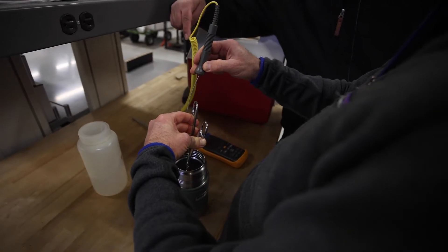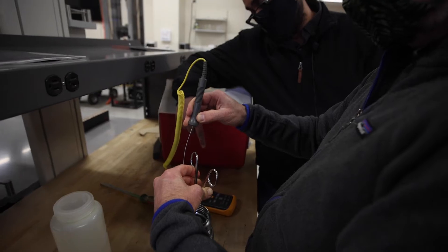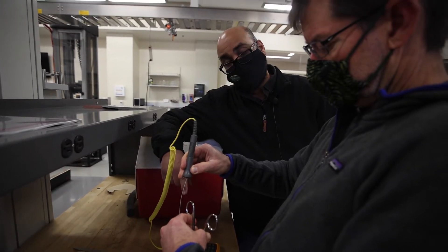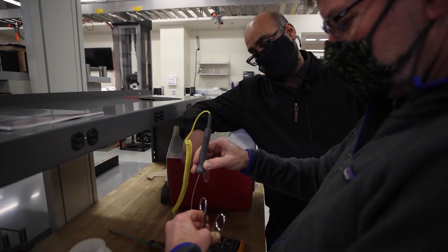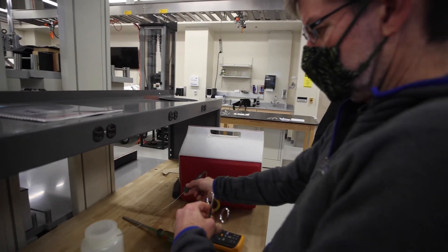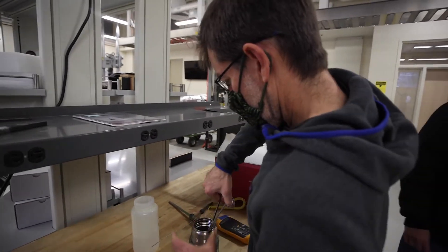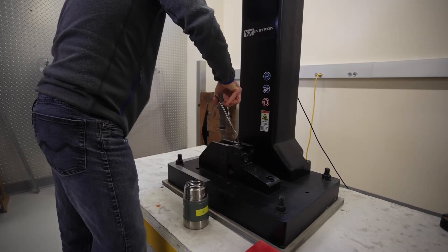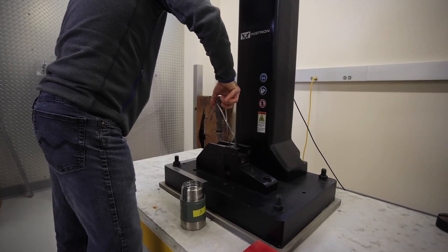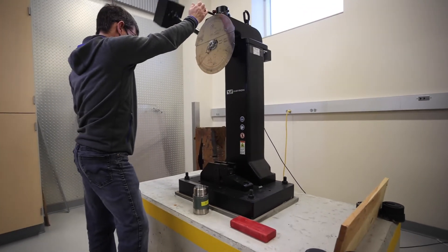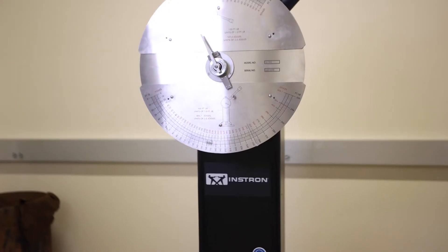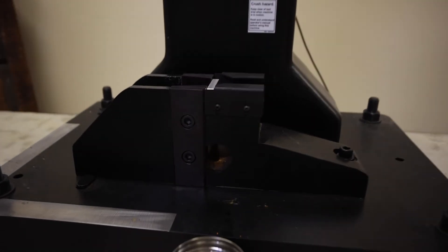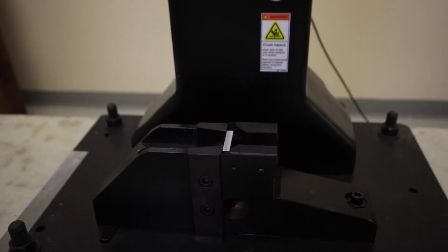We are placing our metal samples inside dry ice, and right now the temperature is about negative 67 degrees Celsius. We have to quickly transfer this sample to the anvil and then pull the trigger and release the hammer to see how it works. For the third set, rather than using carbon steel at two different temperatures, we are going to use aluminum, which is a softer material, and do it at room temperature to see how it behaves.